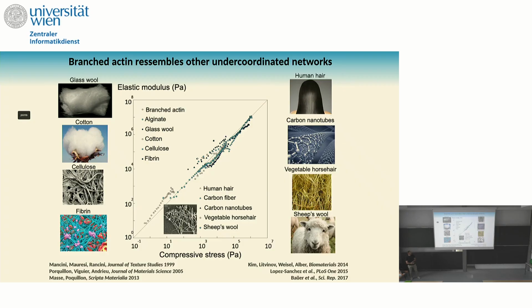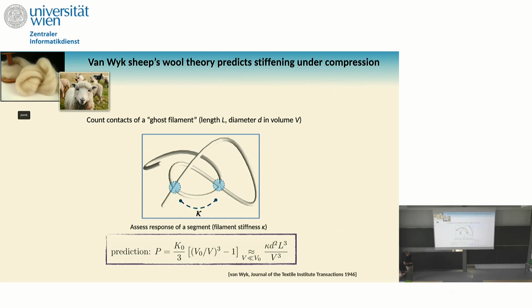If you take measurements from all these filamentous-like networks, going from cotton, cellulose, fibrin networks, carbon nanotubes, sheep wool, what you would find is that they seem to fall onto a master curve. Even though the scales are extremely different, the only analogy between these is that they have this filamentous structure. So this tells you that maybe there is some common physics across all these different scales, from the branched actin at the nanoscale to your hair or the sheep wool when you compress it. And the answer is yes. So to model that, Van Wyk, in the 40s, was very interested in compressing sheep wool and trying to understand how the stress is increasing when you compress the sheep wool.